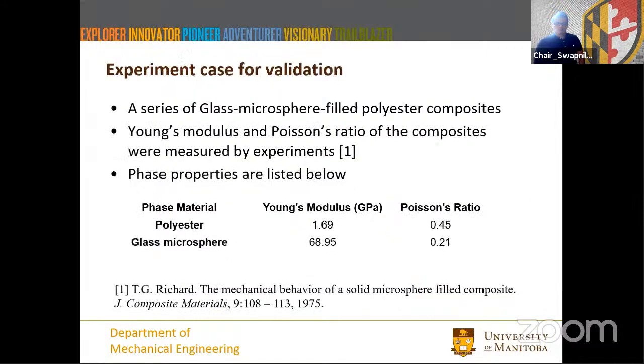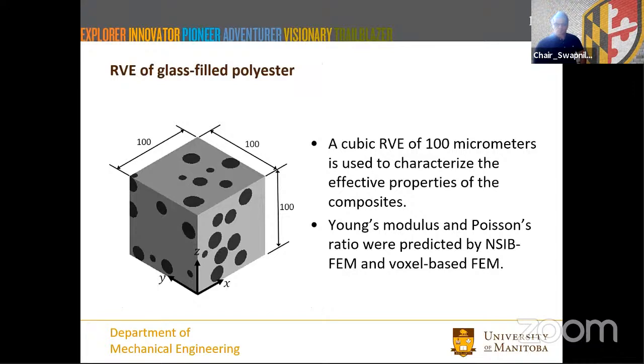We used an experiment case for the validation. The composites are a series of glass microsphere filled polyester with different volume fractions of glass in the polyester. The Young's modulus and Poisson ratio of the composites were measured by experiments, and the phase material properties are available for finite element modeling. A cubic representative volume element of the composites was used in finite element modeling.